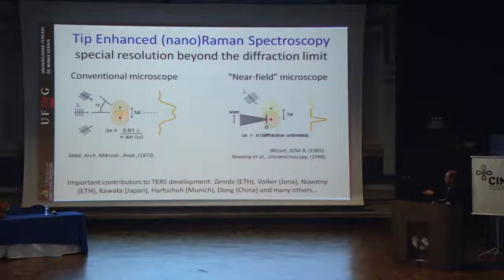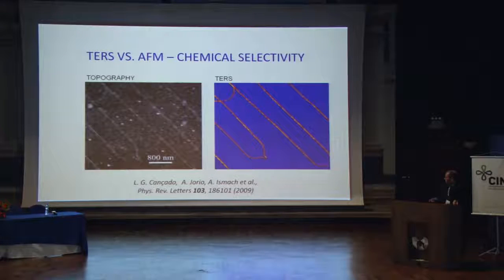And the way you do it is basically, if you have two emitters that are too close together, you cannot differentiate the information from them because of the diffraction. But if you are able to approach a nano antenna and strongly enhance the signal from this emitter, then you can move this antenna from here to here and visualize that one was red and the other was green, okay? So we have been doing this, and this is tip-enhanced Raman spectroscopy, which is not nano-IR, it is nano-Raman.